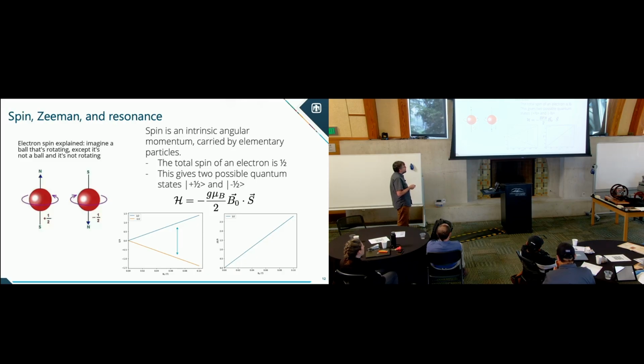So if you look at the energy, and I put this in gigahertz, E over h bar, as a function of magnetic field out to 1,000 Gauss, you get spin minus 1/2 getting lower energy and plus 1/2 getting higher, and you can have a resonance here that depends on magnetic field.